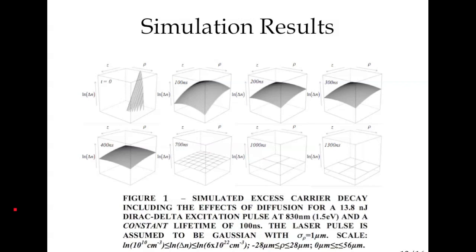So this shows basically what we expect. It depends on the relation between the diffusivity and tau. But we see these are in 100 nanosecond chunks with a tau of 100 nanoseconds. We see quickly that there's kind of this explosion effect, the carriers quickly diffuse outwards, and then they slowly exponentially recombine.